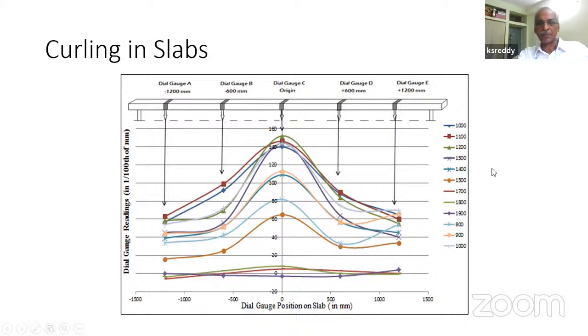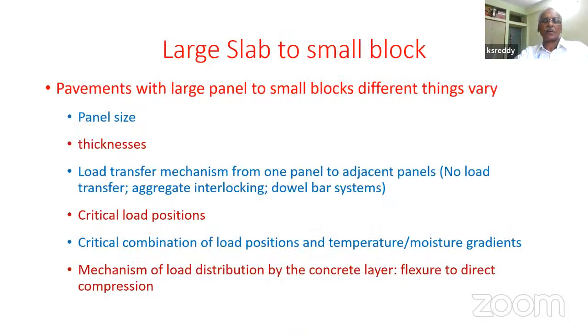So curling happens, but part of this is restrained. This is what is happening after the total curling is restrained partly because of the self-weight and the connections with the adjacent slab and connection to the foundation. So when you compare large slab to small block, the block pavement to the continuous concrete pavement, these are the things that are going to be different. The panel size is going to be different. What would be the panel size is a function of how many joints are activated. So do you have 4.5 by 3.5 or 9 meter by 7 meter slab?